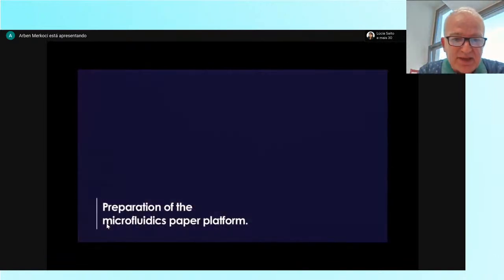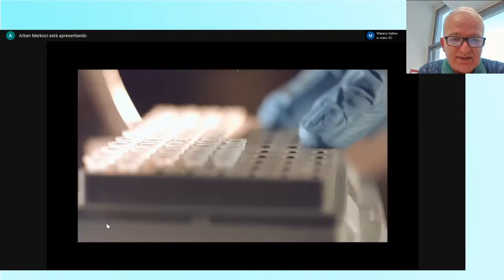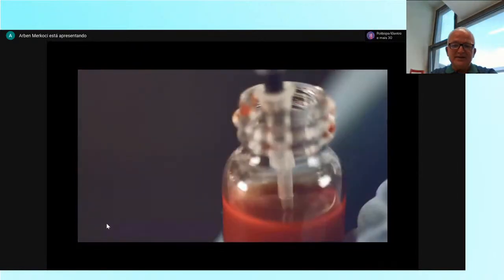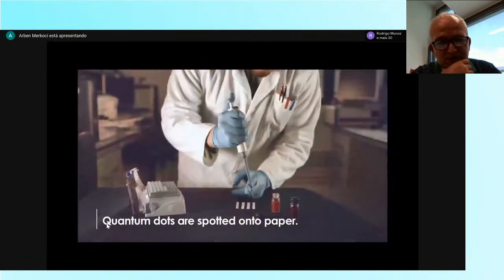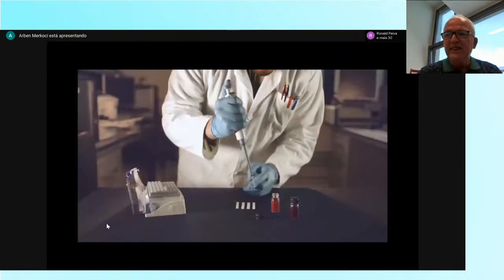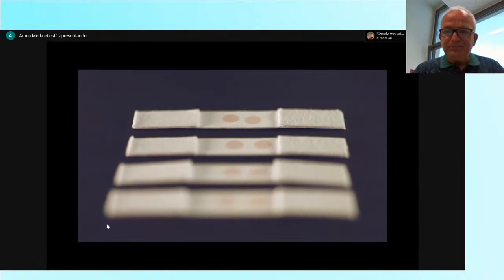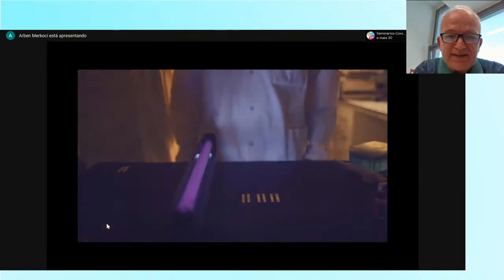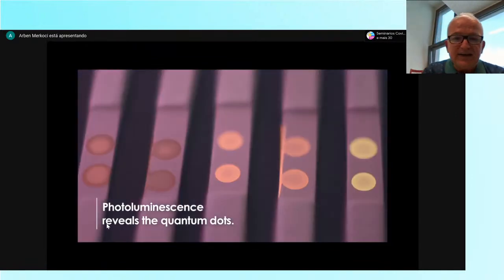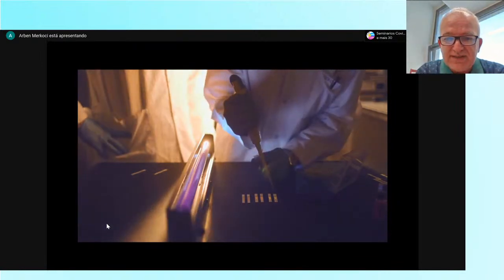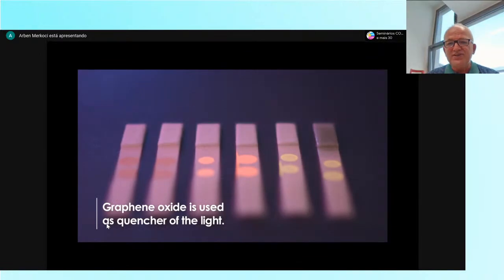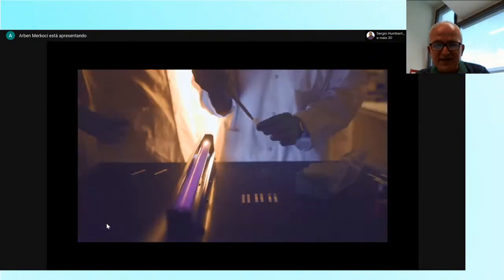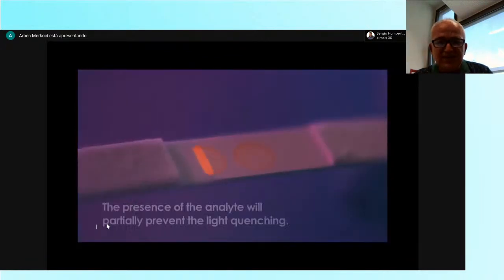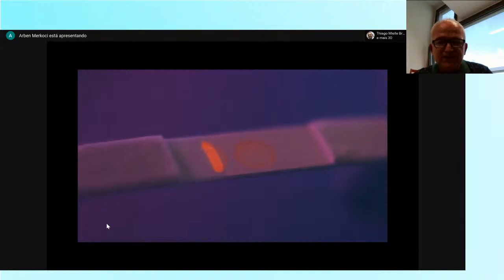So we first prepared the paper-based sensor, set up in a paper of different porosity and building these different pads, of course, sample pads, conjugation pad. Afterwards, we introduce the quantum dots. So in this case, it is a cadmium selenide quantum dot introduced onto the paper. And after excitation, the photoluminescence is revealed. So these quantum dots show very nice photoluminescence that in turn is quenched when we introduce the graphene oxide suspension. You can see here how this photoluminescence is decreased upon interaction with graphene oxide suspension.